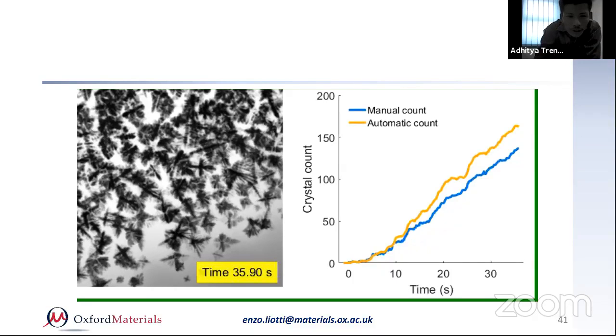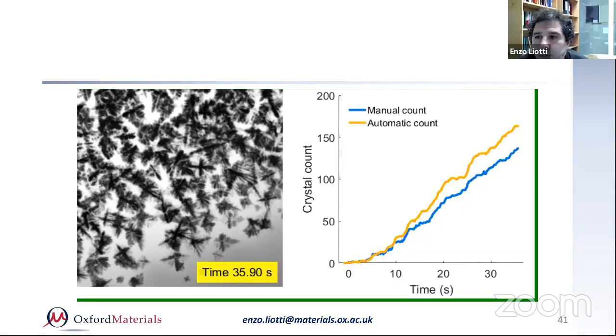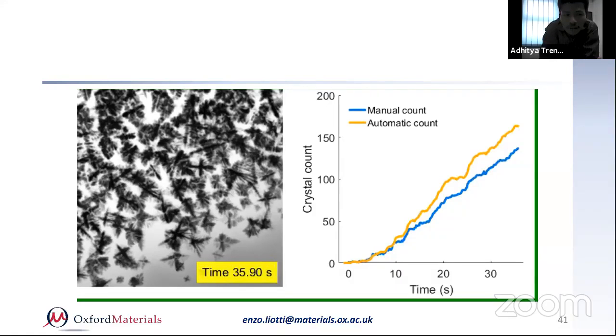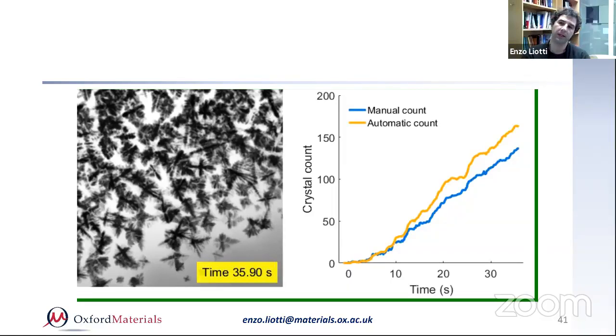And in the setup of the experiment, the substrate is similar to the material of the mold, let's say, in continuous casting, or rather the material of the case of the sample. In this case it was quartz, or we use boron nitride, or any other material that is X-ray transparent and is easy to handle. The capsule is there because if you don't use it, the sample is basically floppy, it won't stay. If you put it vertical, it will just fall down, right?